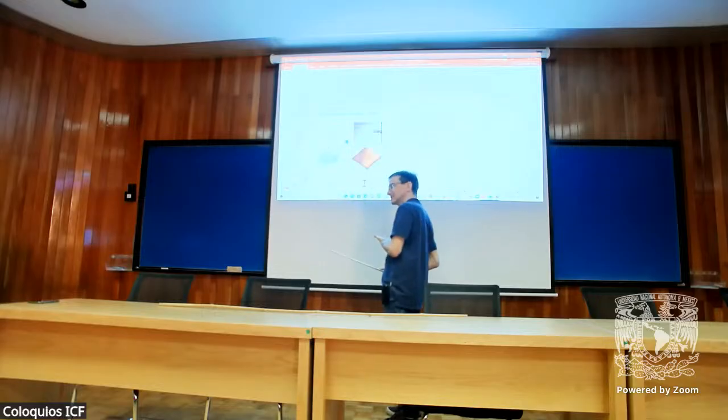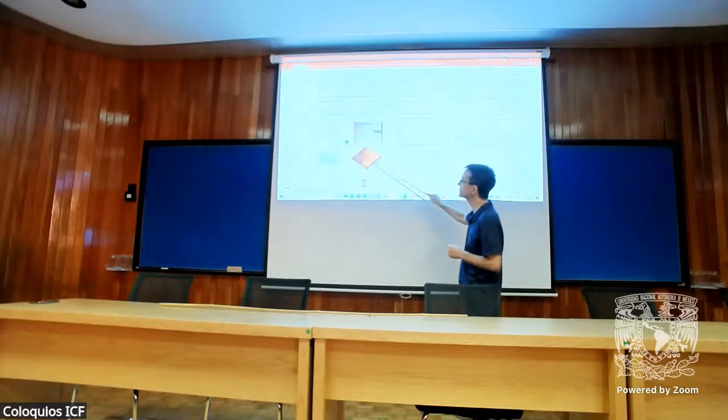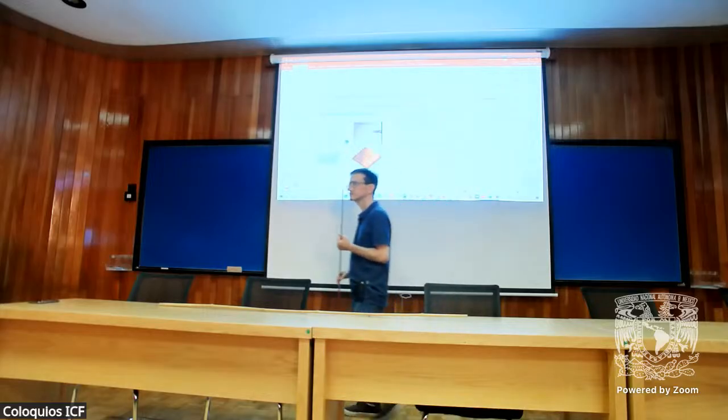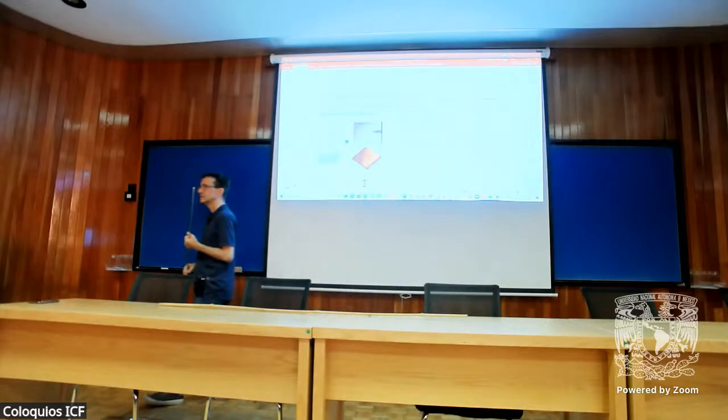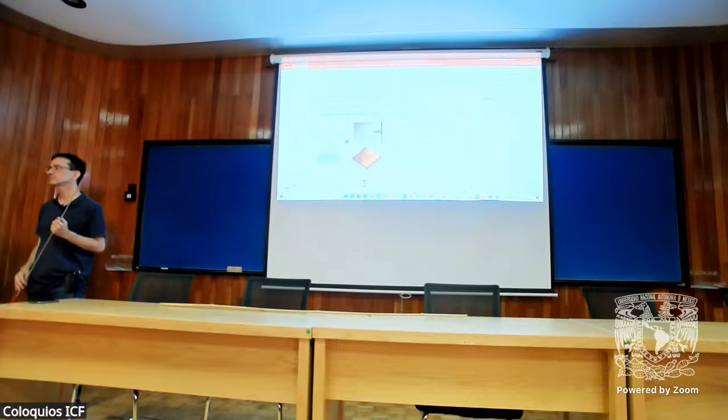This is good in this case because the fluence was really high here, and it goes down in this direction. And this is what we are seeing here. So we later come with a microscope and probe the sample in different positions. When you do that, we are probing as a function of the fluence. And this is a sputtering ion source, a SNICS ion source, working with cesium.